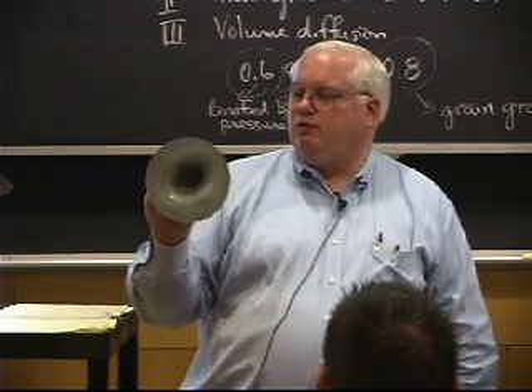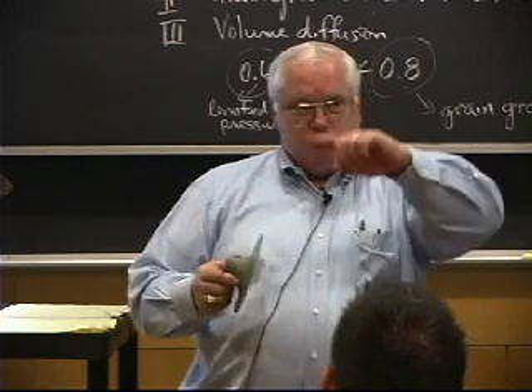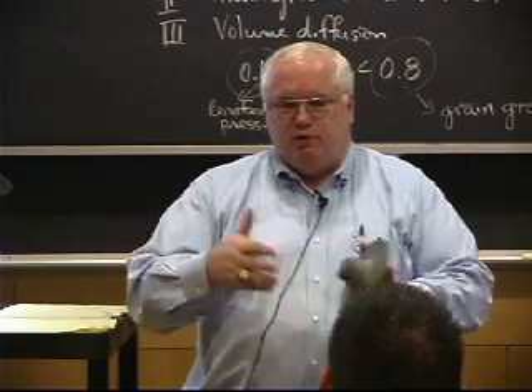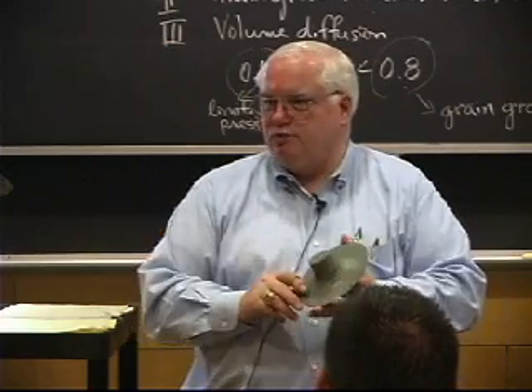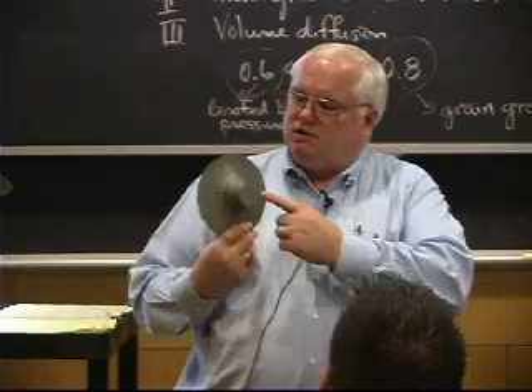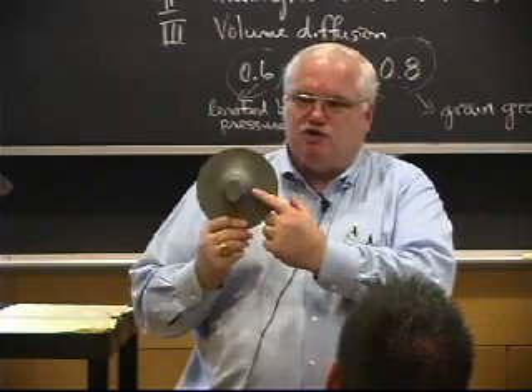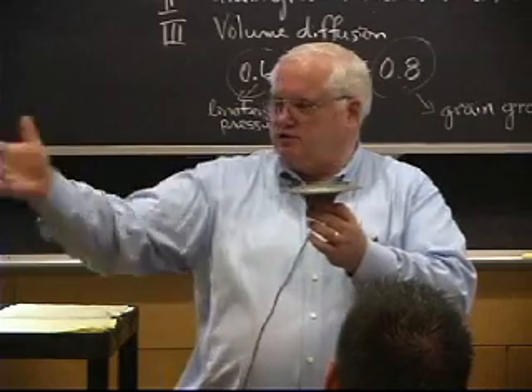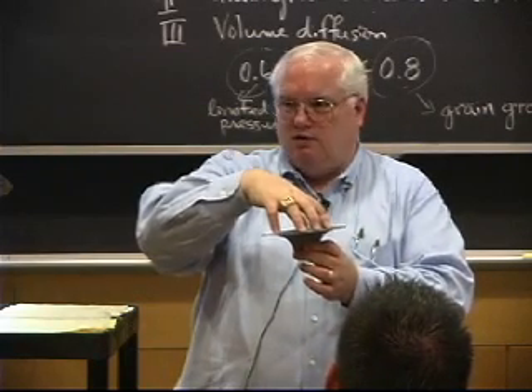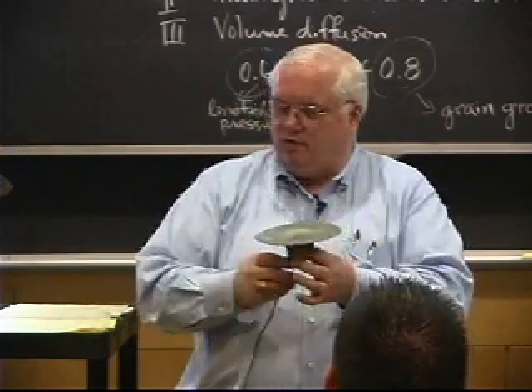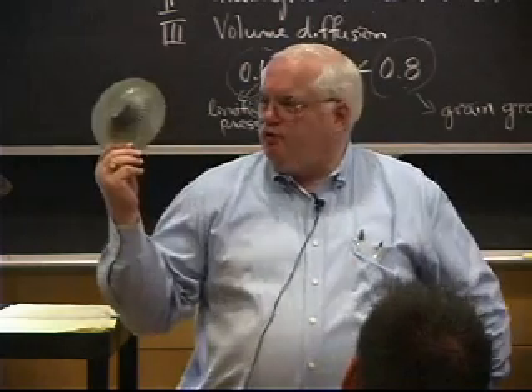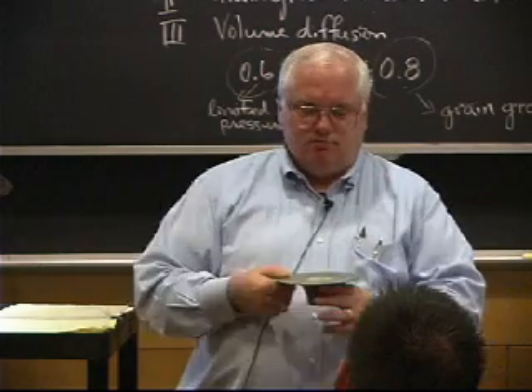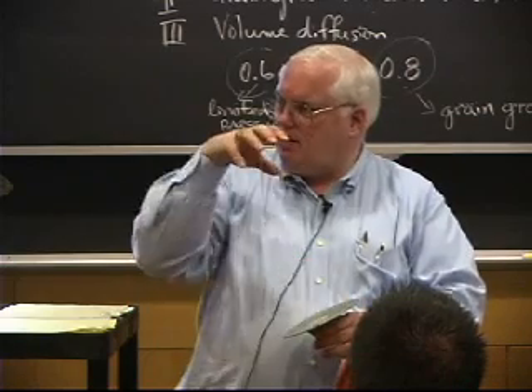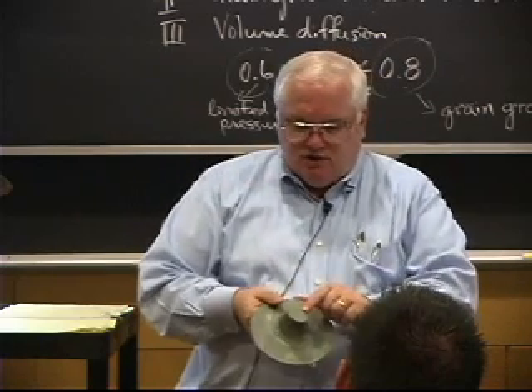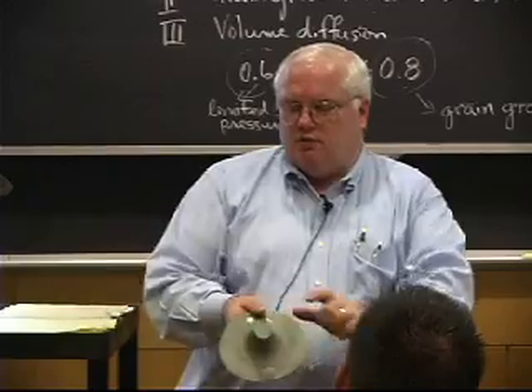In the laboratory he was looking at aluminum zinc alloys, and the Boston area, because of Paul Revere and other people, used to be a big area for silversmiths. It's not as big as it used to be, but he went down to some of the silversmith companies, and this was some sort of little candy dish or something, and ordinarily you'd have 6 or 7 dies to make a silver part like that. And he could basically take the last die, put gas pressure on one side, and slowly form it in there. Actually, you can see it didn't form quite as well around the little corners at the end. Probably could if you left it in there long enough.